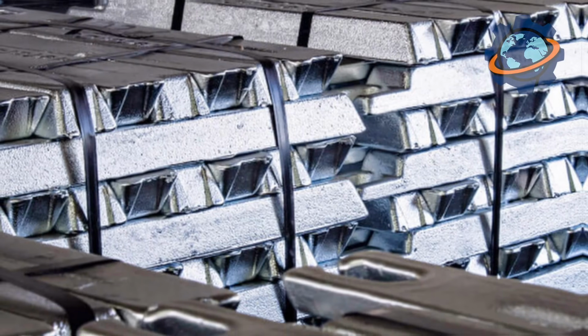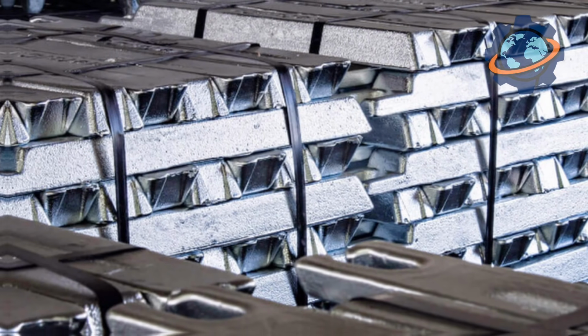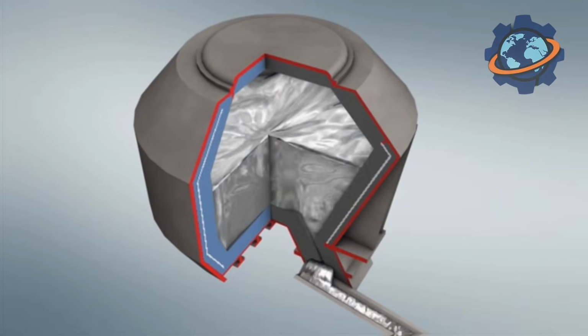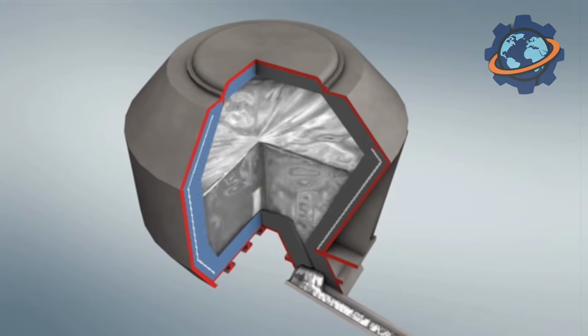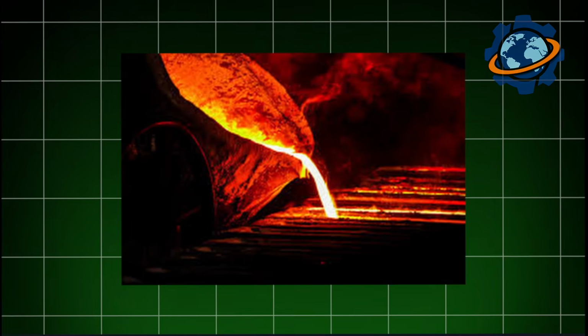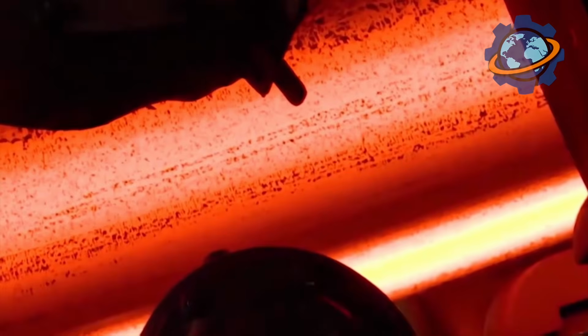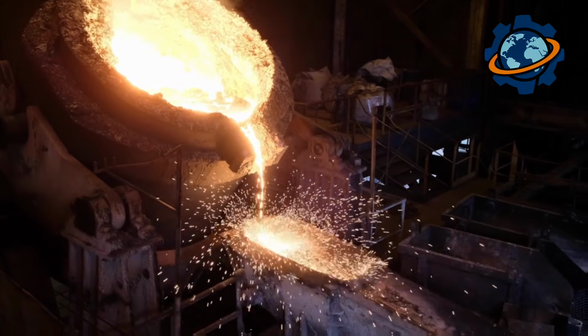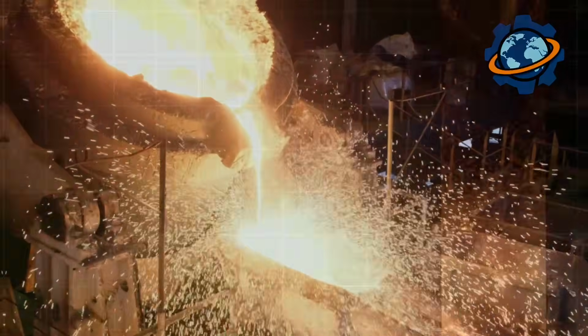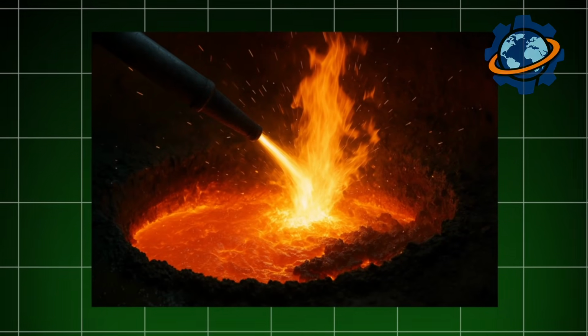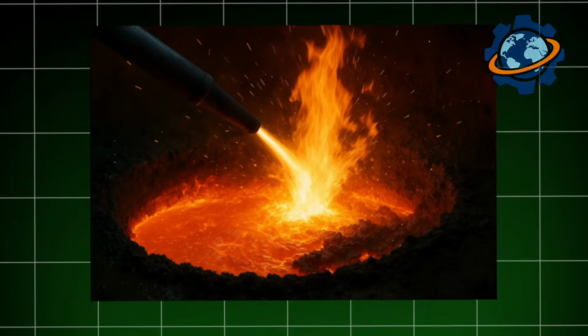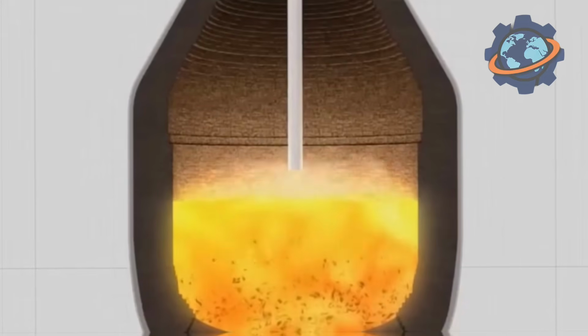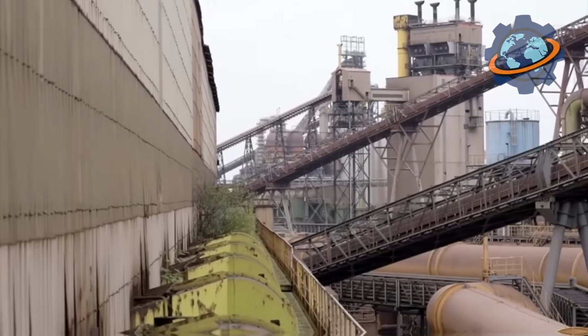Zinc is ready for use. But its main application awaits in hot-dip galvanizing baths. There, steel products will receive corrosion protection. The process looks impressive, like baptism of metal by fire. A steel beam 40 feet long is immersed in a bath of molten zinc. Temperature 840 degrees. The beam completely disappears in the silvery liquid. Chemical reaction begins instantly. Zinc reacts with iron on the steel surface, forming a layer of intermetallic compounds, a solid alloy of zinc and iron.